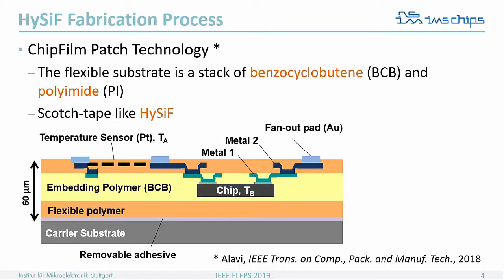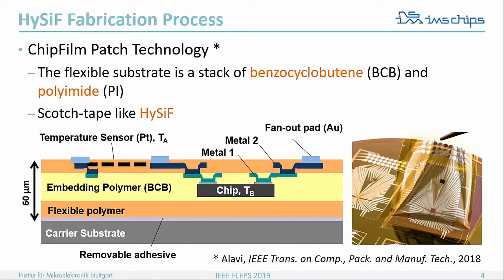The surface is also very smooth, so you will see the quality of the thin films deposited or fabricated on the surface doesn't suffer any degradation because of the surface. And this system could be used as a scotch tape sensor system and can be attached to any surface, in this case for temperature sensing. Also releasing from this carrier substrate: all the fabrication is done on a rigid substrate, but then at the end you can release this system by simple mechanical release or by laser release for more accurate release.